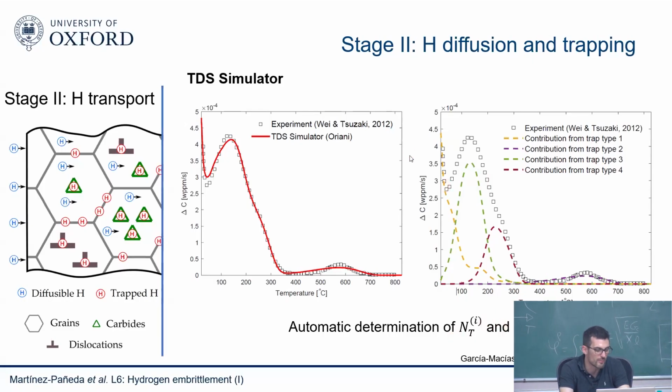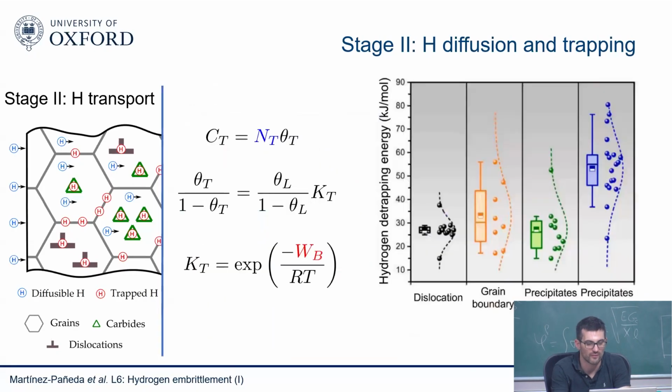And I think the method people were using, called Kissinger, is not really good because it assumes infinitely fast diffusion, and that's obviously erroneous. We are now writing a paper explaining how big the error is, and it's quite large. It depends on your material and so on, but it's quite large. So I think it's important to move towards these tools, and then hopefully we can reduce this big scatter here.